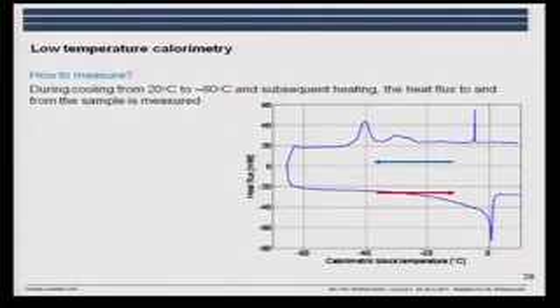So how do we measure? We place a sample in a calorimeter, and then the temperature is gradually lowered. We have a cooling, and we measure the heat flux. And at a certain temperature, the heating takes place, and we have a thawing of possible frozen water.